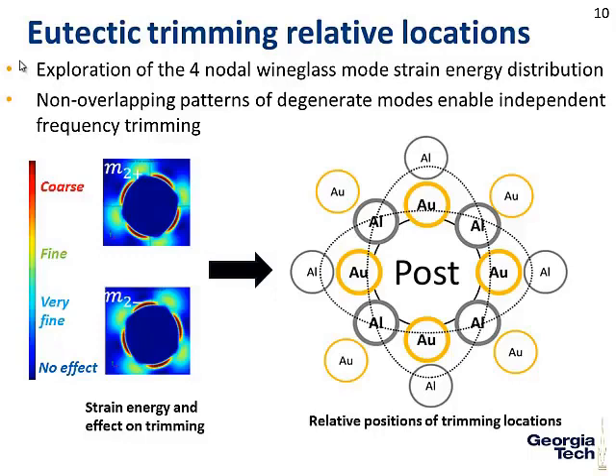And also, last point, if you're going outwards, farther away from the post, you have less and less effect. And finally, you have the coarse effect here and the fine effect here. And you can see that they are located at 45 degrees apart. So if, for example, you're here, the next location will be at a 45 degrees angle and not straight in that direction.